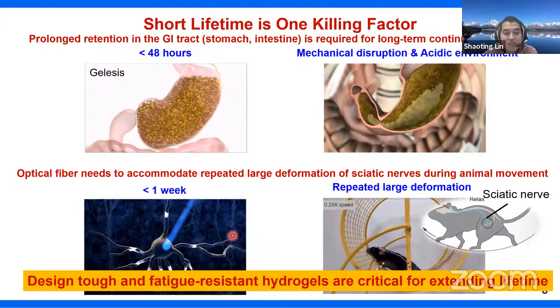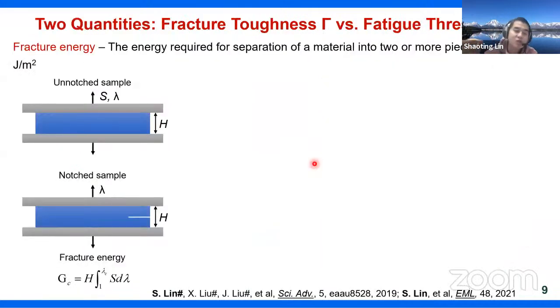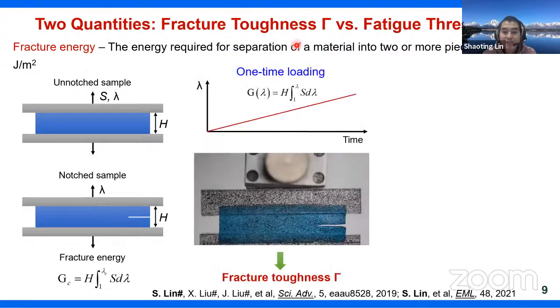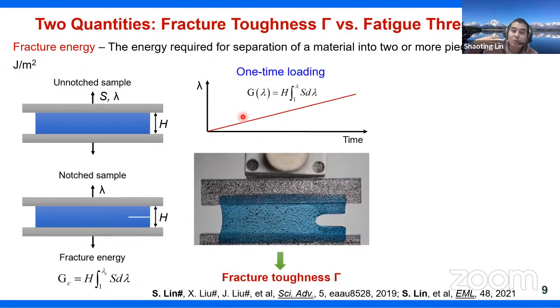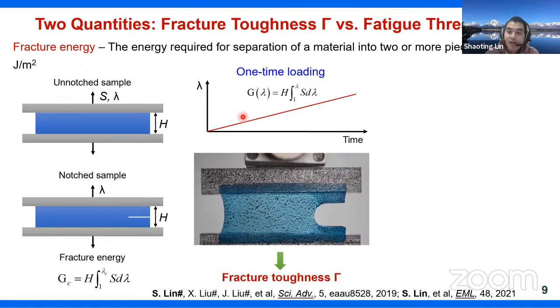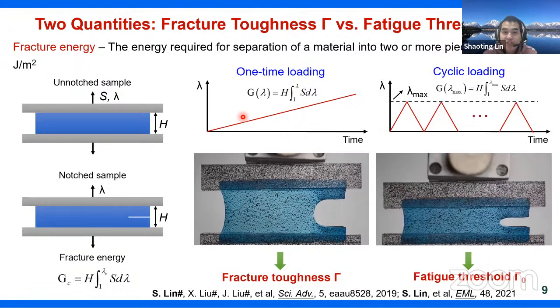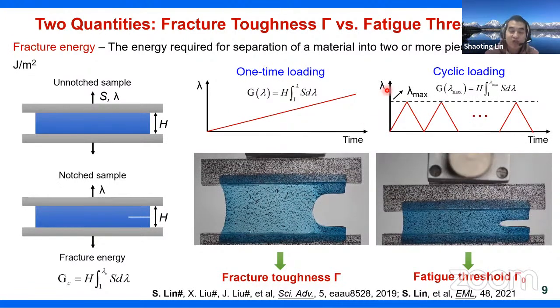The underlying physics behind this application is essentially governed by two quantities. One is the fracture toughness, gamma, and the other one is the fatigue threshold, gamma naught. These two quantities are essentially fracture energy, which is defined as the energy required for separation of the material into two or more pieces, and the unit is joule per meter squared. The difference between these two quantities is that the fracture toughness is defined as the fracture energy measured under one-time loading, and the fatigue threshold is defined as the fracture energy measured under cyclic loading.